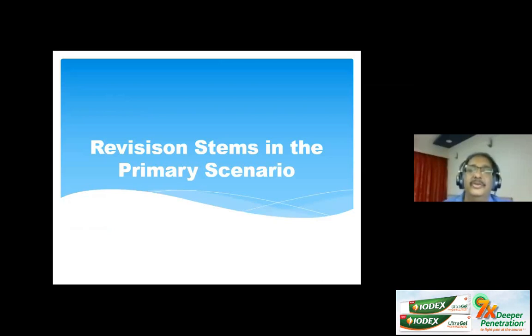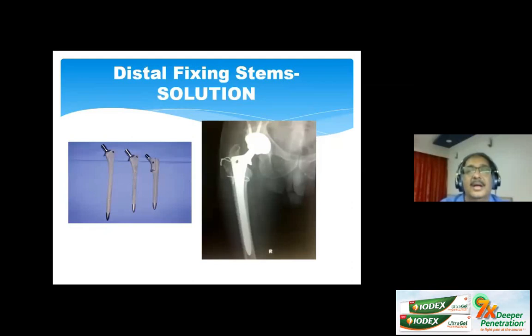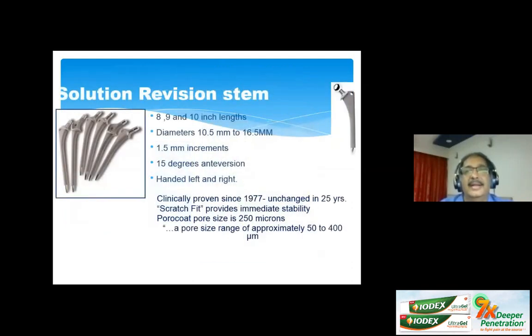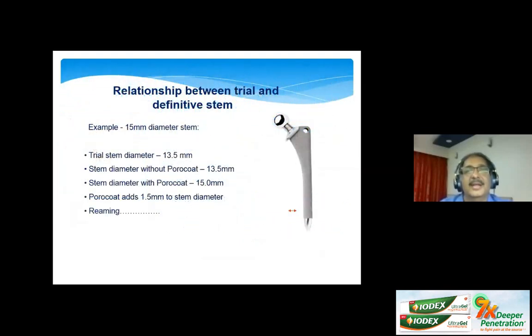Sometimes you may require to use revision stems in the primary hip scenario. So it's better to have some working knowledge as to what we have out there. First of all is a distal fixing chromium cobalt stem, which is called a Solution stem. It comes in 200, 225 or 250 mm sizes, 225 and 250 mm being bowed as per side to accommodate the femoral bow. 8, 9 and 10 inch lengths, 15 degrees anteversion, which is left or right. And the diameter of the stem is 1.5 mm more than the implant trial that you use.